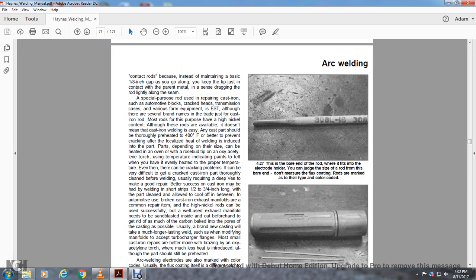Even there can be cracking problems. It can be very difficult to get cracked cast iron clean before welding. Welding usually requires a deep V to make a good repair. Better success for the cast may be had by welding short beads, 1/2 to 3/4 inch long.